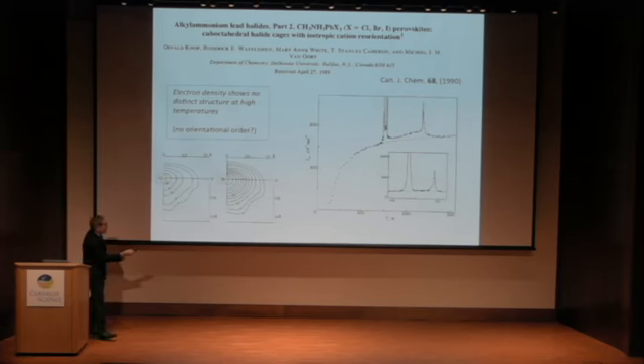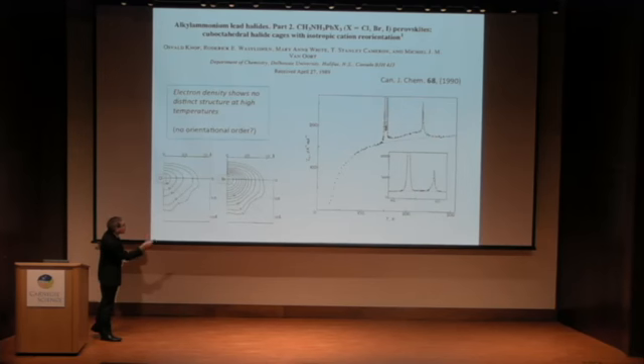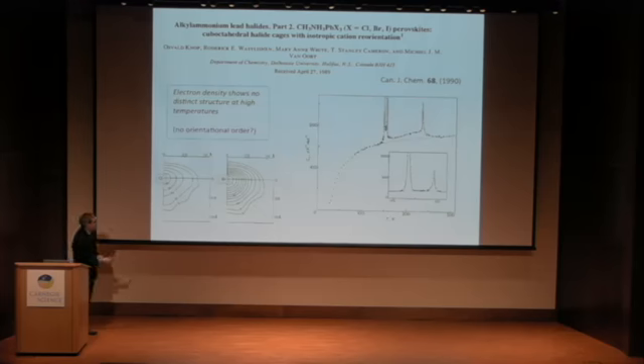Now, people with keen eyes might notice that this isn't actually one peak here. It's actually split into two. So there's actually another phase transition. And this intermediate phase going from the orthorhombic to the tetragonal phase is a bit of a mystery. I think at the moment there is some consensus from diffraction that it's some sort of incommensurate phase, but at least to my knowledge, and I might be wrong on this, and if anyone has comments about it, I'd be really interested to hear, no one's actually solved the structure and worked out what this intermediate phase is.